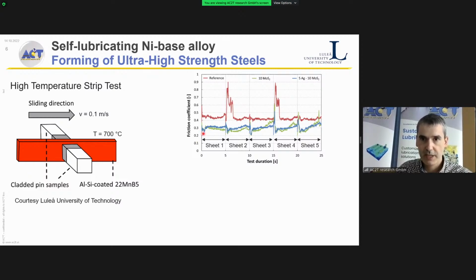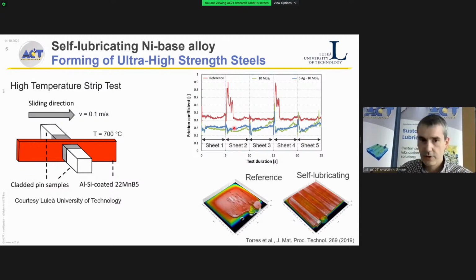And when we use the self-lubricating one, in this case the blue line, we have a much lower friction, around 0.3 for every sheet, and when we change the sheet, we also don't have this break-in friction. We also get a change in the wear mechanism, and we switch from adhesive wear, which is very detrimental in forming processes, to mild abrasion.